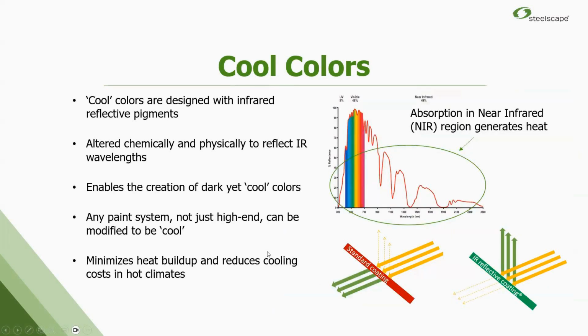Cool colors, so cool pigmentation. These were introduced about 20 some odd years ago now. This is pigmentation that has been modified to reflect the infrared part of the spectrum, which is where you get heat buildup from. So we were able to keep the color of the pigment the same, the dark colors, but not get as hot. So basically we were able to create a black that stayed cooler in the sunlight and still looked black, which was kind of a game changer for our industry.